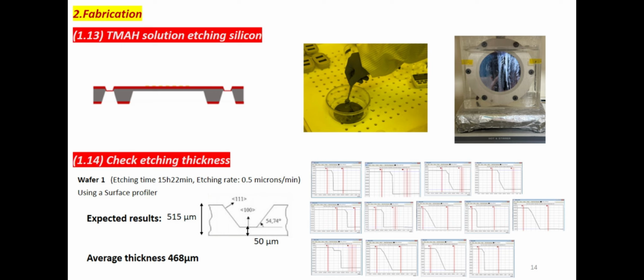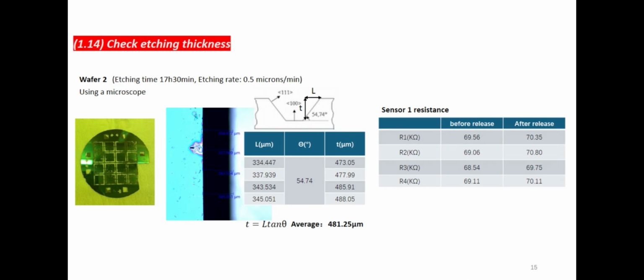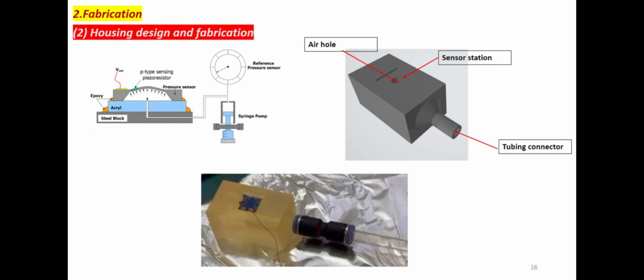The first wafer was etched about 468 micron, and the thin film was about 50 micron. The thickness of the second film was checked under a microscope, and according to the calculation, the film thickness was approximately 481.25 micron. To test the pressure sensor, the housing needs to be designed to firmly fix the sensor and make sure the pressure is applied correctly to the diaphragm.